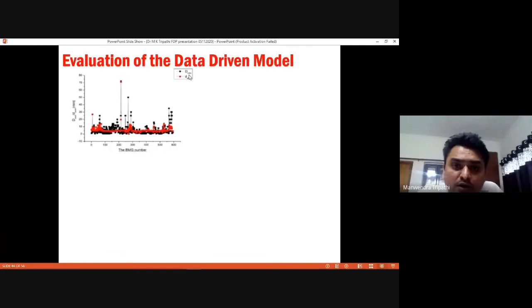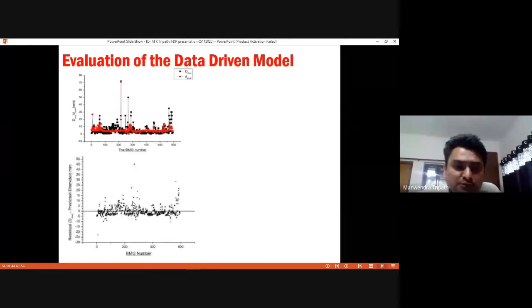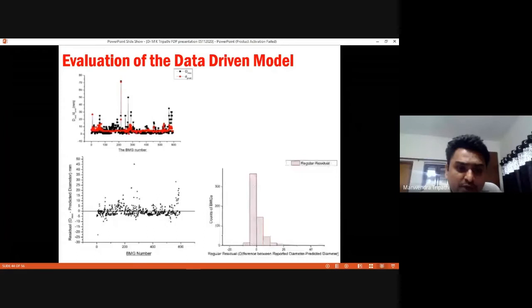and your experimental diameter. We find that there is correspondence, but there are several cases where there is large deviation. So we have tried to capture this deviation. See, these are the BMG numbers, 594 cases, and here is the deviation in terms of mm. So this is the 0 line. Ideally all the points should fall at 0, but if you check, within an error of plus minus 5 mm diameter, many BMGs are falling, right? And another way is that I have counted the cases, maybe around 400 BMGs fall within the band of plus minus 5 mm diameter. So we assume that this is a good fitting, okay?